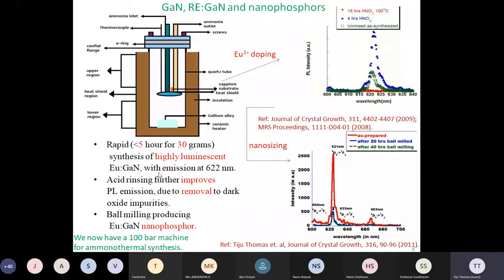Okay, so you can use this kind of a system designed using phase diagram. So it turns out it's a gallium bismuth system, and you can add a tiny bit of europium also into the alloy. You have to homogenize the alloy and flow ammonia through it for a few hours, and lo and behold, you get europium doped gallium nitride with an emission at 620, which is red color, by the way. So this is how we made a device out of it.